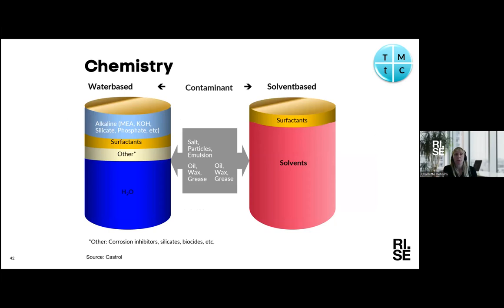First of all, we have to look at what type of contaminant we are to wash away, if it's oil, wax, or grease from previous process steps, or if it's salt particles or other contaminants. There are solvent-based and water-based cleaning liquids, and as you see in the picture, mainly solvent and surfactants in the solvent-based one, but a more complex formulation in the waterborne example here. So except for water, which is the majority of the content, of course, we have surfactants and alkaline components and others, here with a little asterisk, for example, corrosion inhibitors. And if we have a water system, you might need to add some biocides or other additives, so to say.